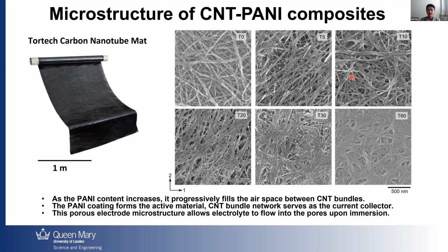As you can see here, as the PANI content increases, the air which is shown in the original mat is gradually filled by the PANI materials. This PANI forms the active material, and the carbon nanotube bundle itself acts as the current collector. These porous electrode microstructures allow the electrolyte to flow into the pores upon immersion, so they are perfect structures for this type of structural power composite.